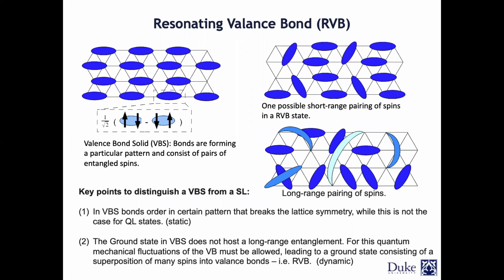Now, this is important because if the symmetry is not broken, sometimes in experiments, if there is a candidate that shows, for example, a non-magnetic or disordered state, then by looking at whether the symmetry is broken or not, we can distinguish whether it is really a viable quantum spin liquid candidate or not. Again, remember the absence of magnetic ordering, even at the lowest temperature, is just a null result, right? We can just look at it and say, okay, there are no magnetic peaks, there's no magnetic ordering, but there are still a lot of different things that we need to consider.